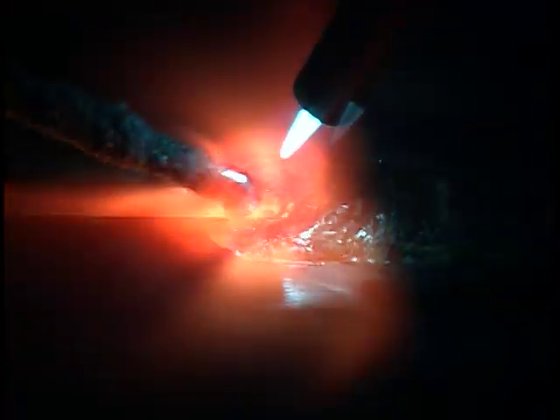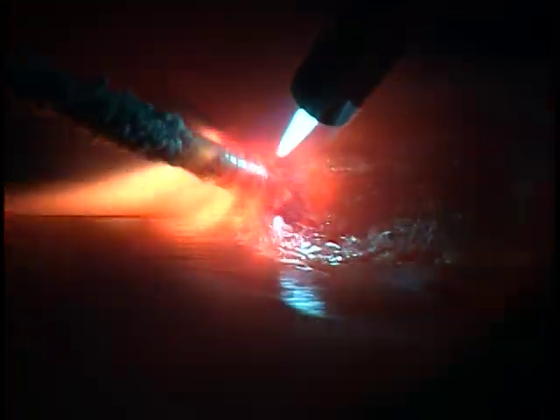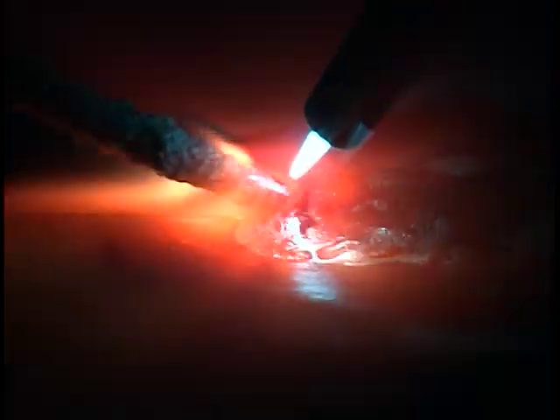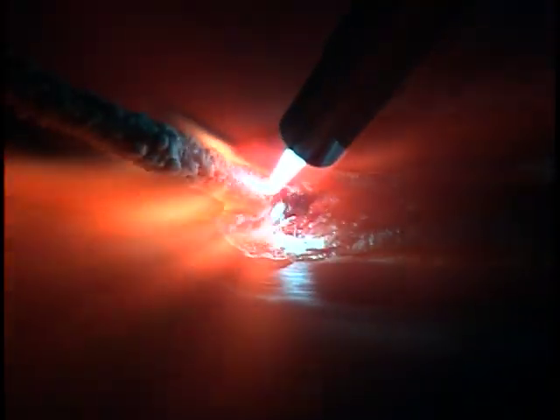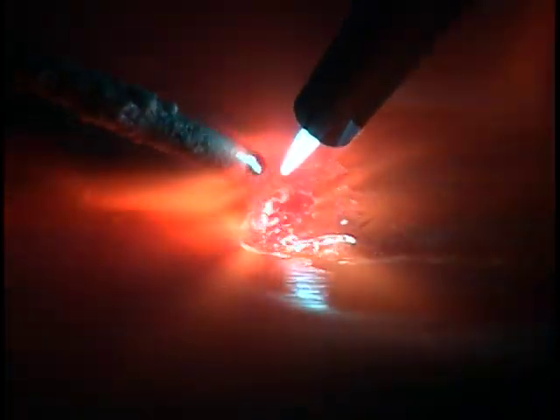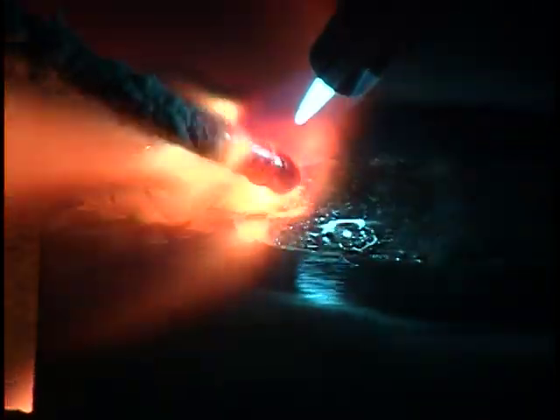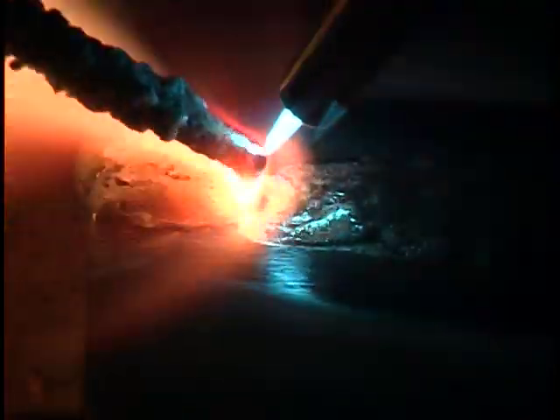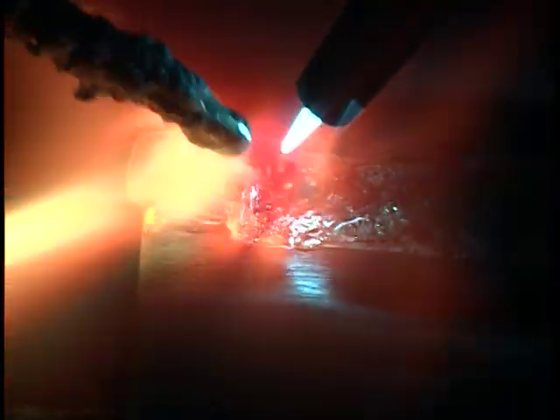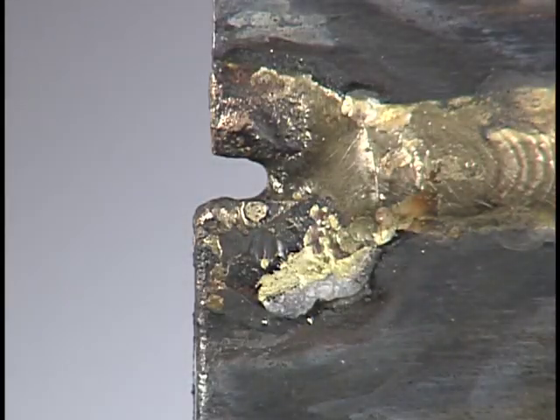Travel smoothly down the center of the joint. Direct the flame so that both plates are bonded by the filler metal to produce a weld face that is approximately 3/8 to 1/2 of an inch wide. Upon reaching the tack weld at the end of the joint, melt into the tack by about 1/16 inch, and then add filler as needed to fill the puddle to the proper bead height. Gradually reduce the heat on the puddle, then remove the flame. If you travel too slowly into the tack weld, you could melt through the tack.